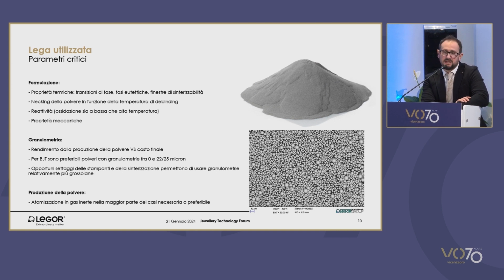Well, the heat characteristics of the alloy are fundamental because they define the sintering temperature. The type of alloy also defines the possibility of eutectic low melting phases that could compete with a medium low temperature phase for the elimination of the binder. In a while I will show you some examples. And then of course the reactivity of the material that defines the type of atmosphere within which I can work during the debinding and the sintering phase. Granulometry.